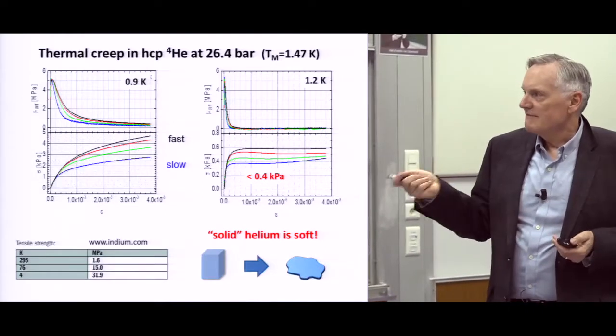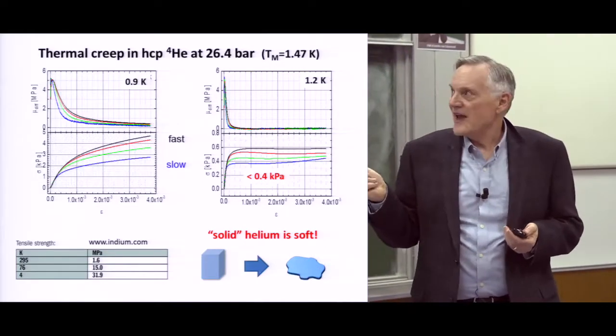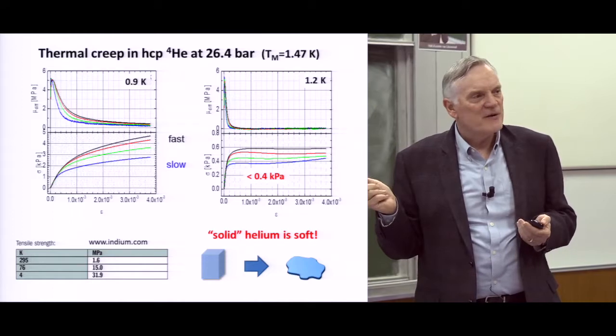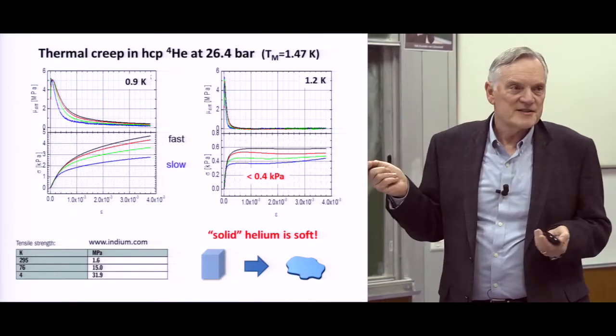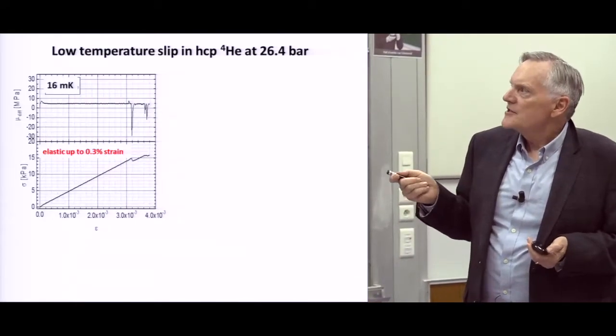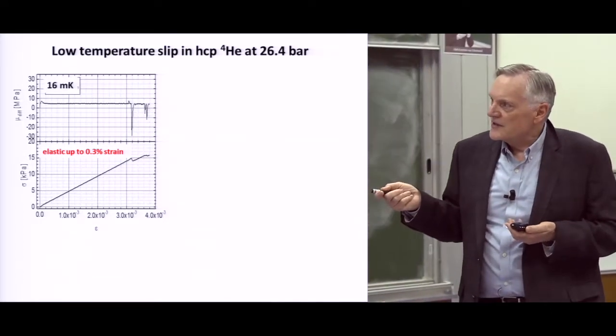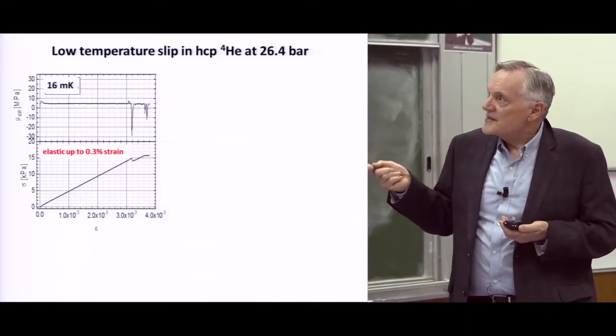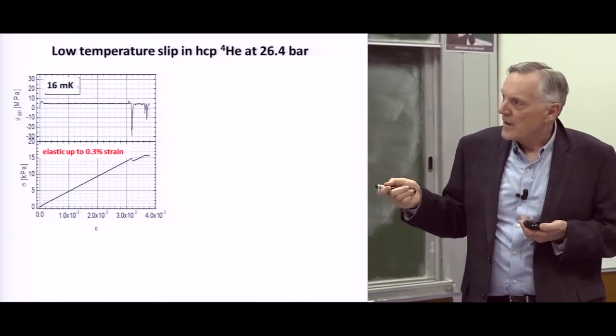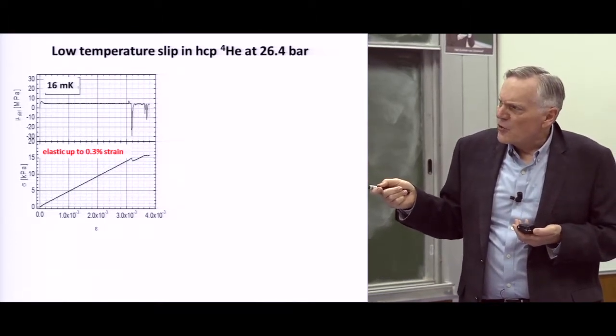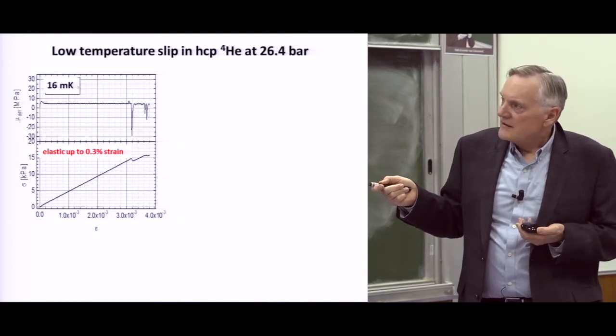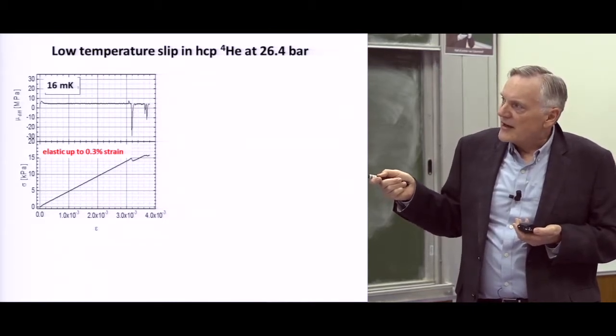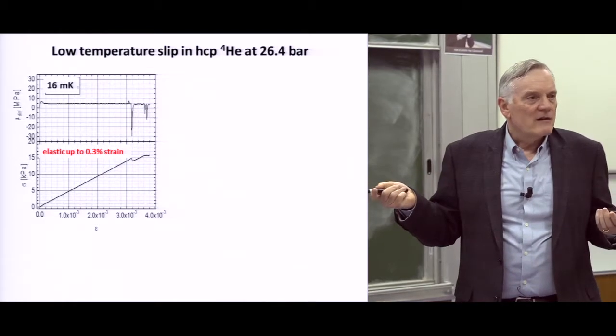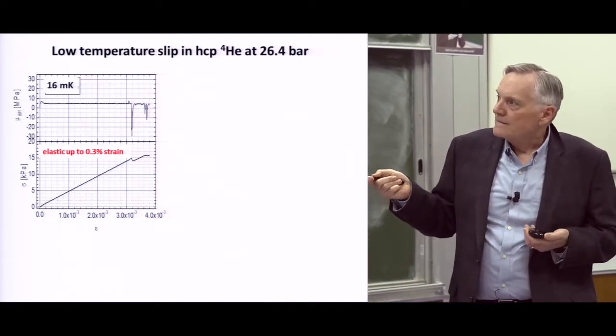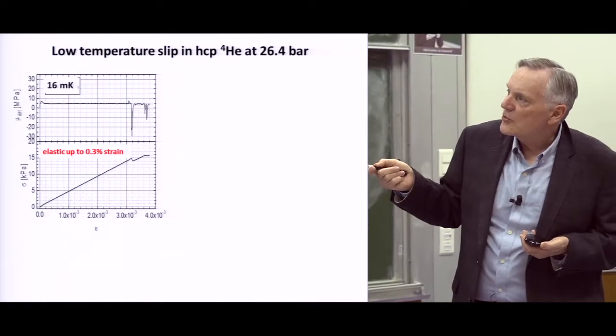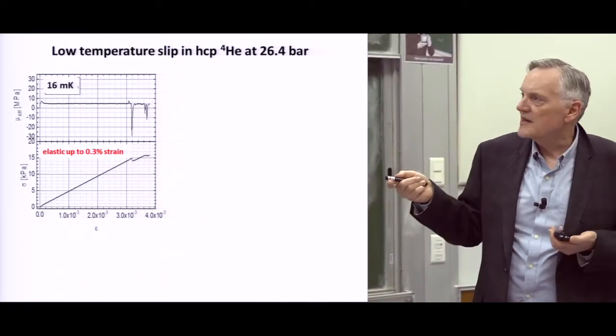Okay, so the most interesting thing, though, is when we tried to answer the question: at low temperature, does it behave that way or is it brittle? And we honestly didn't have a good guess. So what we did is the same kind of measurement, the stress versus strain, only this is at 16 millikelvin. All that data I showed you before is flowing way, way down here. At this temperature, it stays linear and elastic to much, much higher stresses and strains. The stress here is 15 kilopascals instead of a few pascals that you might expect.